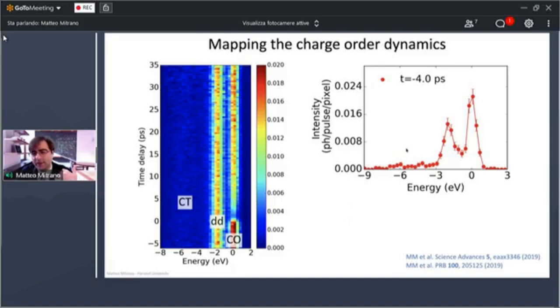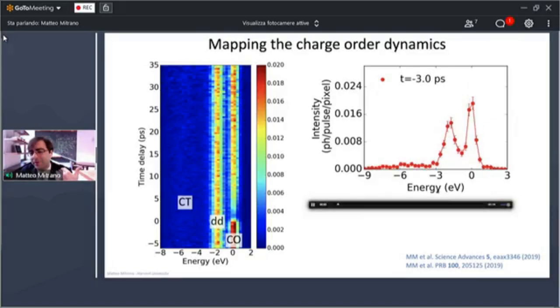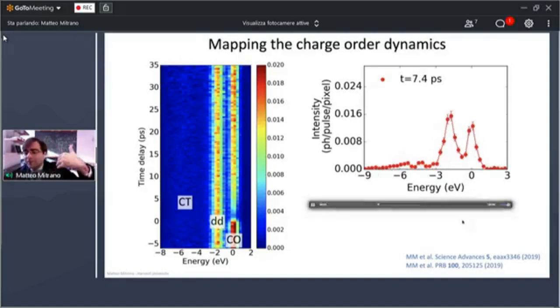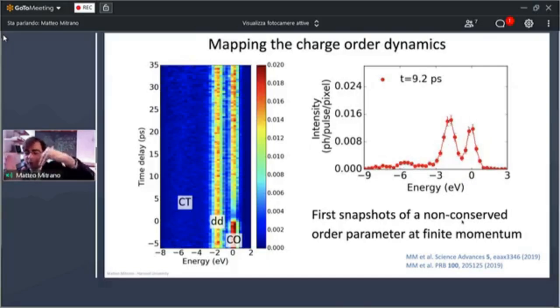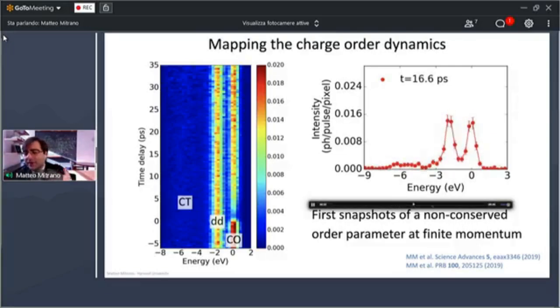And what you can see here on the right of the screen is actually a first movie of the dynamics of this order parameter. So we can really see this peak at zero energy loss that is suppressed by the pump, and then recovers really slowly. I will tell you more about the recovery in a second, but just let me tell you that this is really the first time that we have been able to make a movie on a picosecond time scale of a non-conserved order parameter at finite momentum in these materials. And the recovery is extremely slow because in order for this order parameter to form, it has to annihilate topological defects that are really hard to get rid of.